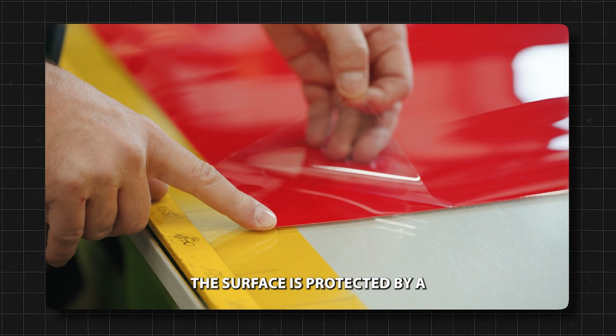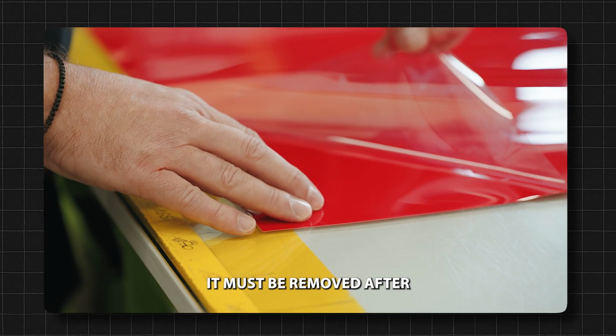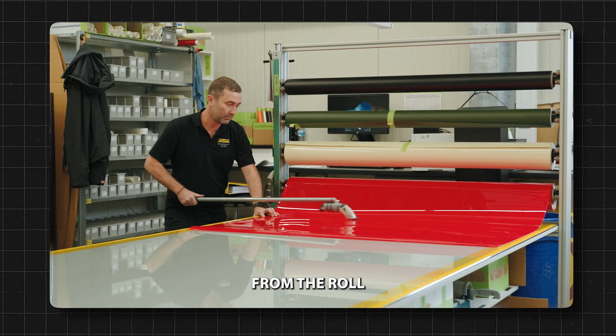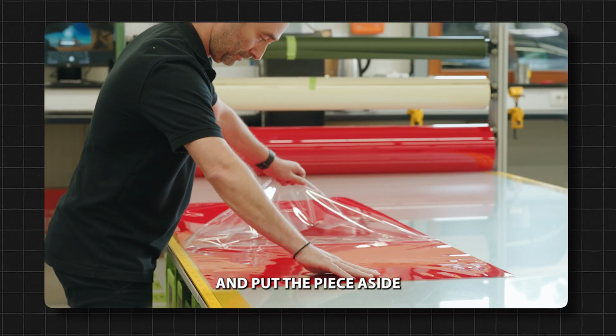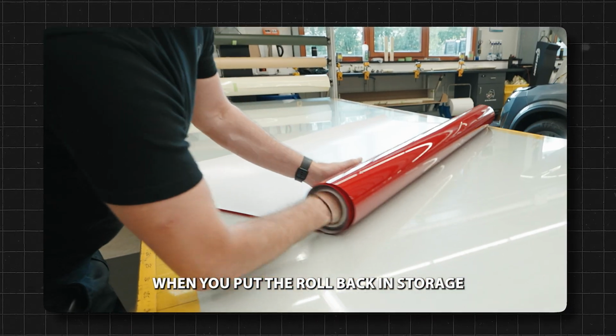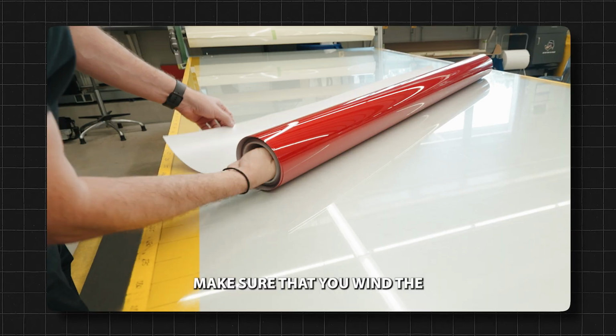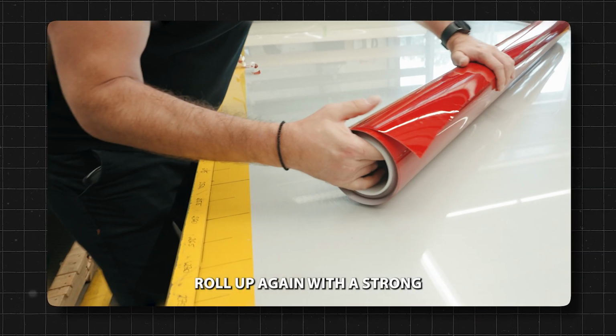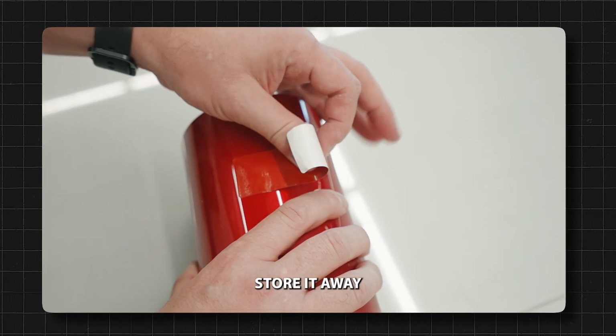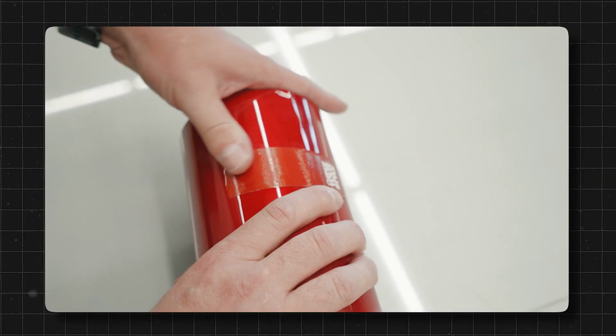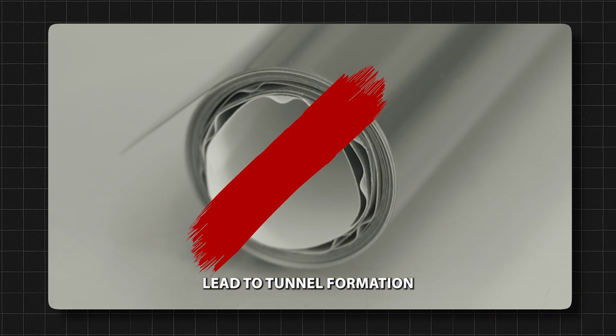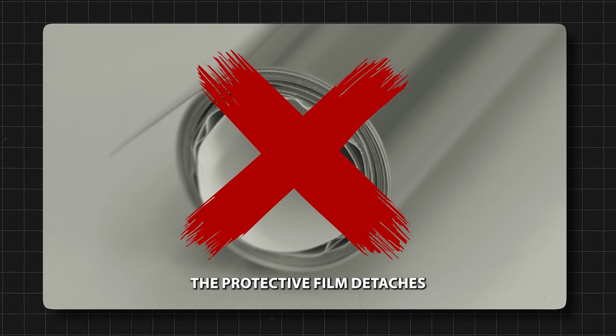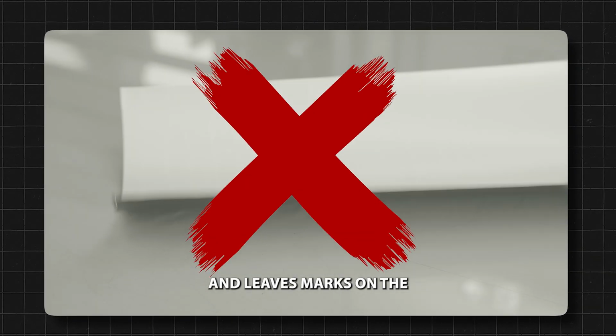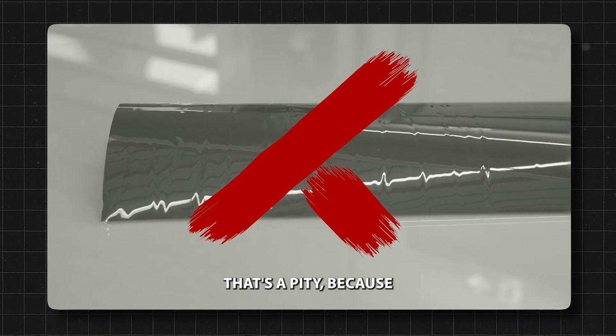When handling the glossy foil, notice that the surface is protected by a protective film. It must be removed after you cut the foil from the roll and put the piece aside. When you put the roll back in storage, make sure that you wind the roll up again with a strong roll tension, and only then store it away. If you don't, it may lead to tunnel formation because the protective film detaches from the foil surface and leaves marks on the surface. That's a pity, because the material is unusable afterwards.